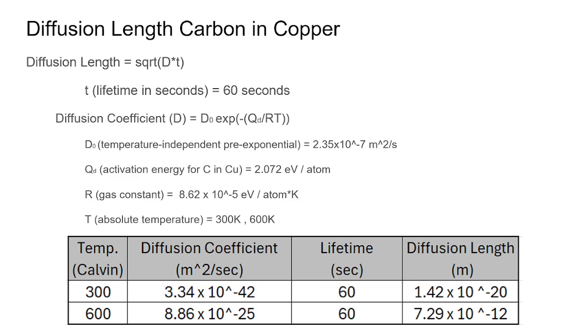So looking at the table on the bottom, you can see that at 300 Kelvin, the diffusion coefficient would be 3.34 times 10 to the negative 42. The lifetime would be, again, the 60 seconds. So plugging those into the diffusion length formula, you get a diffusion length of 1.42 times 10 to the negative 20 meters.